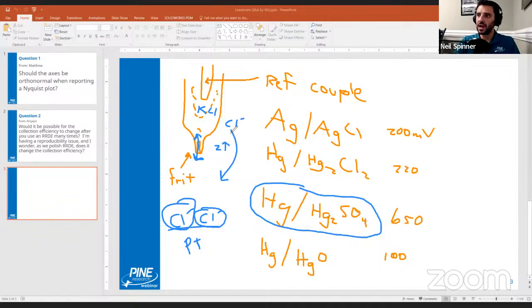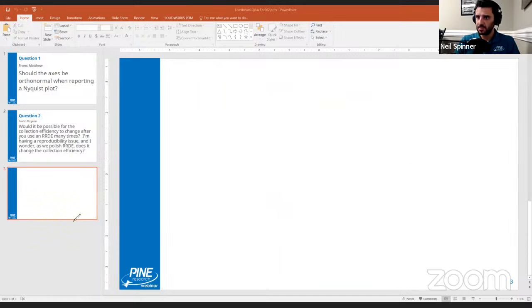Frit, ions, and there's ways to get around this, like double junction and salt bridges. This conversation can go for a lot longer. I'm going to cut it off here. But basically, when it comes to the reference electrode, the main things you're trying to be concerned about are making sure it's in proper working order, making sure the frit is in good shape, making sure you've chosen a stable electrochemical couple, and making sure that there's some compatibility between the supporting electrolyte and your main electrolyte. Often you'll try to pick a reference electrode with a supporting electrolyte compatible with your main electrolyte, so that if there's any crossover or contamination in either direction, you don't have it cross over into your reference electrode and make your reference electrode work more poorly. So that's hopefully a relatively brief overview of that question.